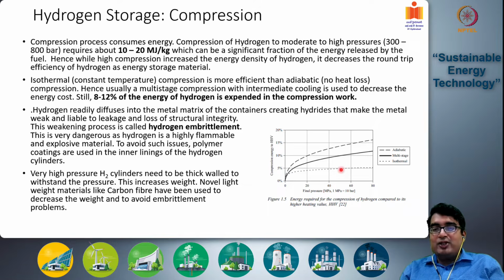So this multi-stage compression process has better efficiency and hence it consumes lower energy. But still, if you are going to around 700 bars, you will lose around 10 to 12% of the heating value of hydrogen in the compression process. So in general, therefore, 8 to 12% of the energy of hydrogen is expended in the compression work.